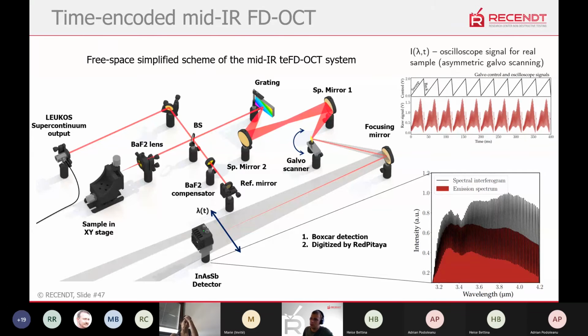Finally, this is how the system looks when it's integrated into OCT. We have another source and our microscope interferometer, here with a barium fluoride lens. Because the band was extended a lot, I clearly observed the effects of group velocity dispersion, and that was compensated using a window in the reference arm. Then we have our scanning interferometer, and such a configuration of Fourier domain OCT. So it's still Fourier domain OCT. It's called time-encoded. We had some discussion on the naming, but it seems to be a reasonable name for this system.